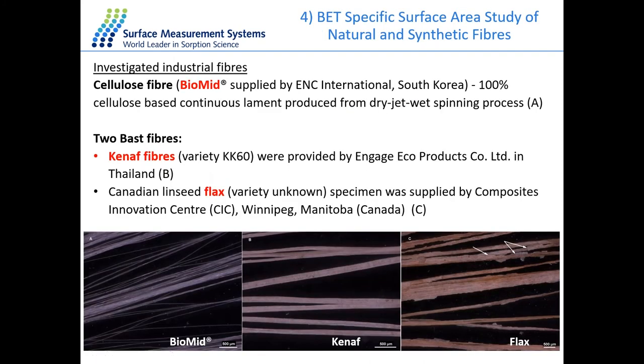In the next example, we have the natural and synthesized fibers, and we want to measure the BET surface area of different kinds of fibers. Here we have three different fibers: the synthesized cellulose fiber, the Biomid sample, and two natural fibers, the Kenaf fiber and the Flax fiber. Here we have the SEM images of all three fibers. As you can see, the Biomid sample and the Kenaf sample are quite neat and clean on the surface. It's very smooth on the surface.